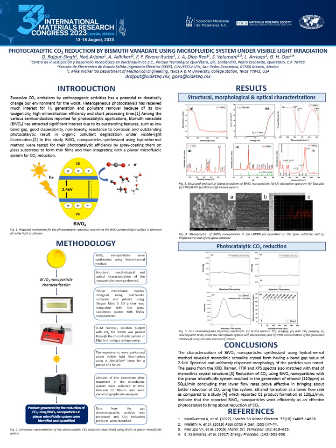about its reduction. For assessing the photocatalytic activity of bismuth vanadate, first the nanoparticles were synthesized using the hydrothermal method. Later, they were characterized structurally, morphologically, and optically to identify the exact crystalline form of the nanoparticles. Then a planar design of the microfluidic system was developed using SolidWorks software, and the model was printed with resin with the help of a 3D printer. The nanoparticles synthesized were then deposited with the help of an air spraying technique, and they were then integrated with the microfluidic cell to be further used for carbon dioxide reduction experiments.